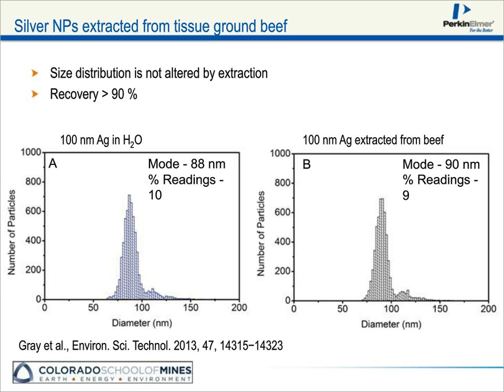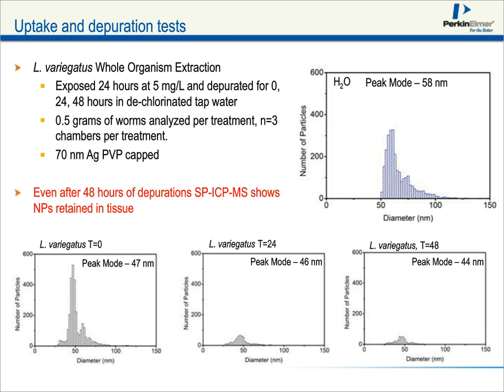We used a worm, Lumbriculus variegatus. We exposed it to silver nanoparticles. The nanoparticles are shown on the upper right, just suspended in water. After 24 hours of exposure, we took these organisms and put them into clean water to depurate what might be present in the gut. But you can see at the lower left at time 0, the worm before depuration, we can see the particle size distribution and the particle number concentration.